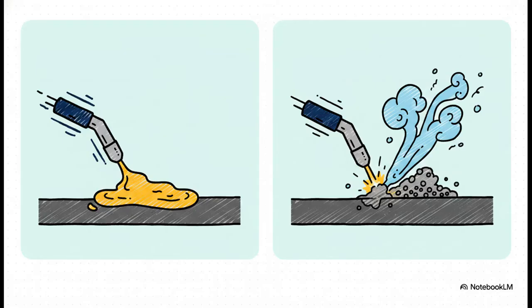Now, you also need to know exactly how your technique triggers those other penalties. If you're suffering from lack of fusion or cold lap, it's very often because your travel speed is just too slow. The puddle rolls ahead of your arc, creating a thermal barrier. On the flip side, if you are getting porosity, those tiny, maddening trapped gas holes, it's highly likely your arc length or contact tip to work distance is just too long. When your arc distance gets too wide, it breaks the gas shield, allowing atmospheric nitrogen and oxygen to just rush in and completely ruin your weld.